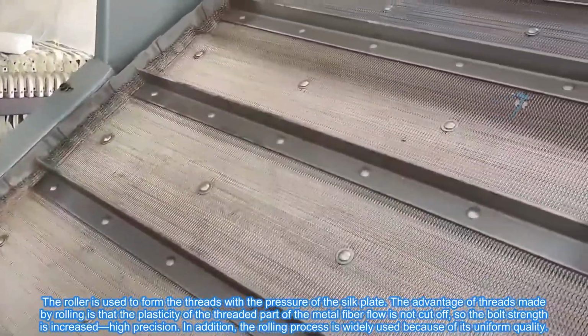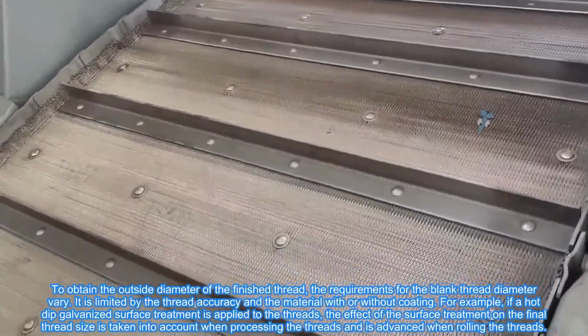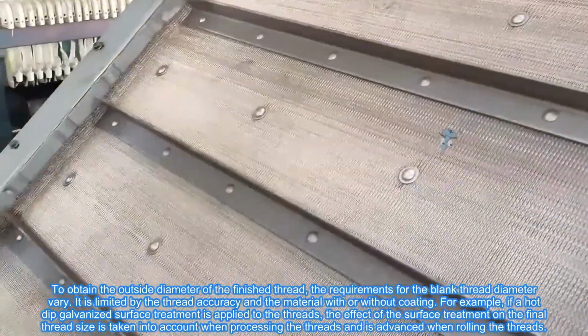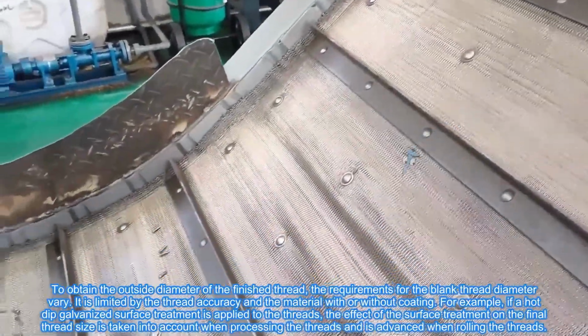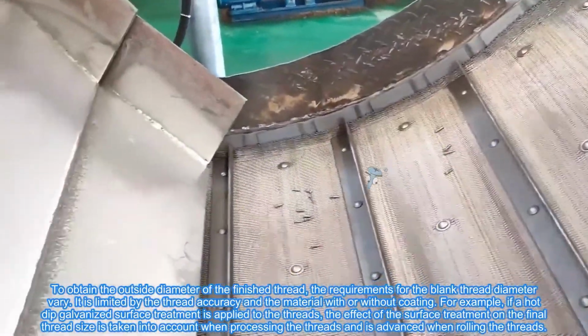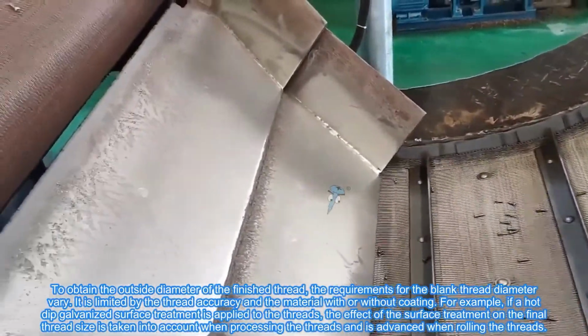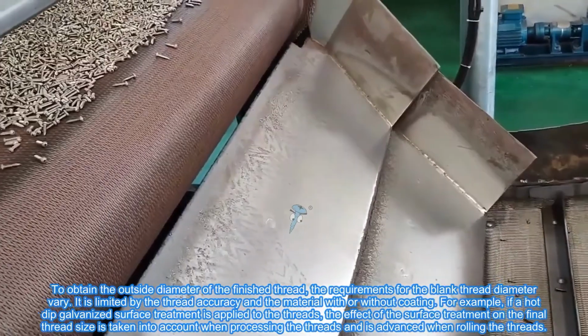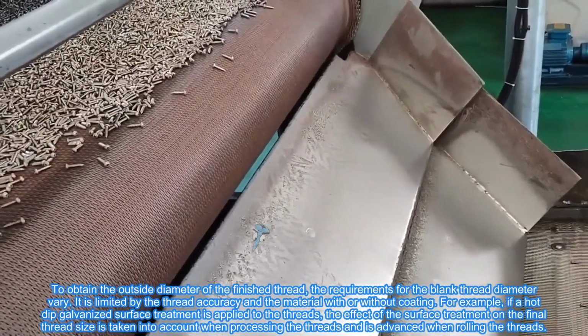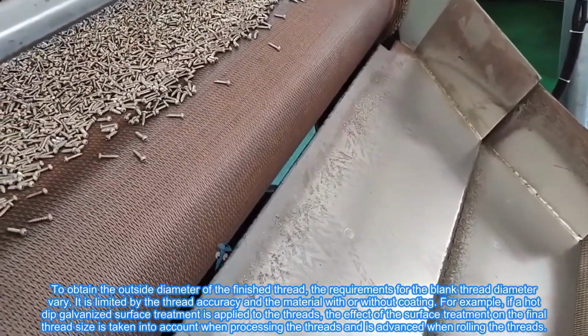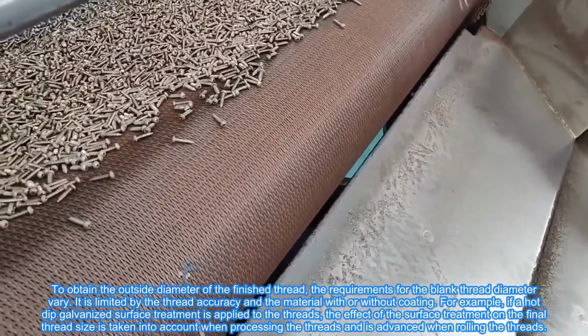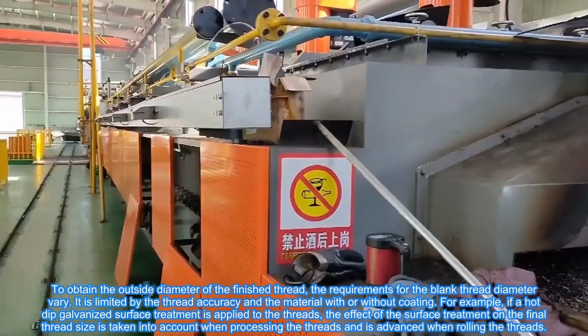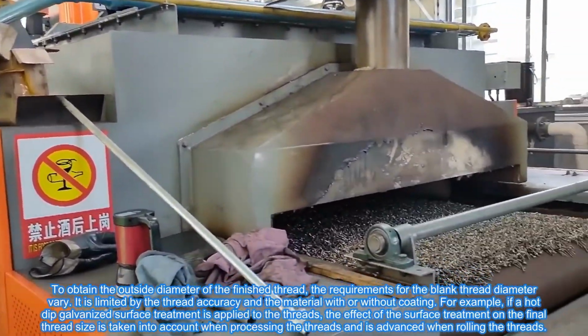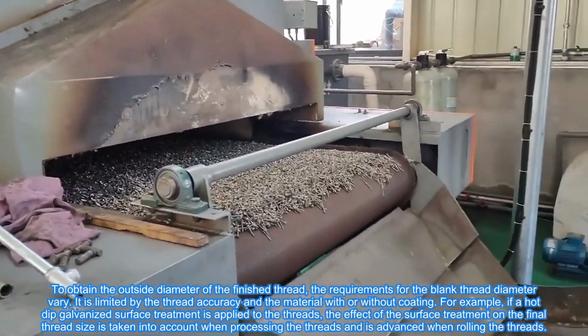To obtain the outside diameter of the finished thread, the requirements for the blank thread diameter vary. It is limited by the thread accuracy and the material, with or without coating. For example, if a hot-dip galvanized surface treatment is applied to the threads, the effect of the surface treatment on the final thread size is taken into account when processing the threads, and is allowed for in advance when rolling the threads.